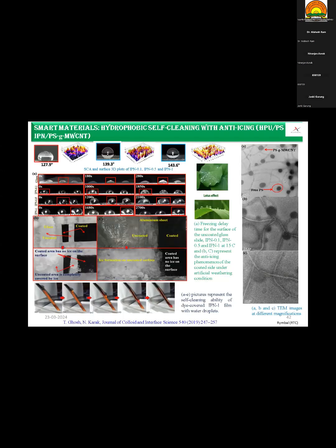This system of nanocomposites not only cleans the surface by superhydrophobicity, but also helps to delay ice formation. You know that during winter, or in winter countries where the weather is very cold, it is difficult to keep instruments or engines in working condition because of the low temperature and ice formation on the surface. So we have seen that if you coat these superhydrophobic nanocomposites onto your device, then it will delay ice formation significantly.